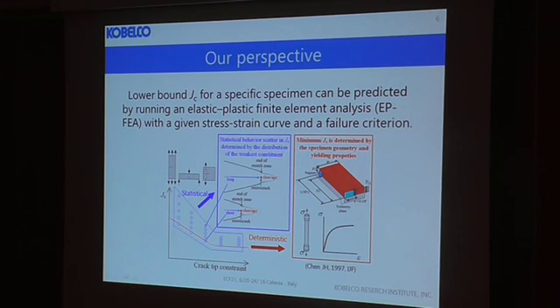We first sought to re-examine Chen et al.'s opinion that it is necessary to distinguish the concepts of the minimum toughness, or the lower boundary of toughness value, from that of the scatter band of toughness. The former is a definite parameter determined by specimen geometry and yielding properties, and the latter is statistical behavior determined by the distribution of the weakest constituent.